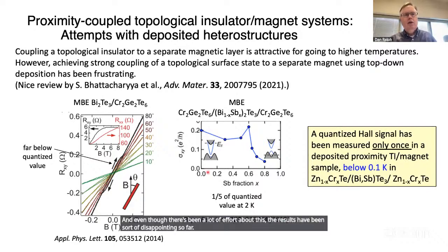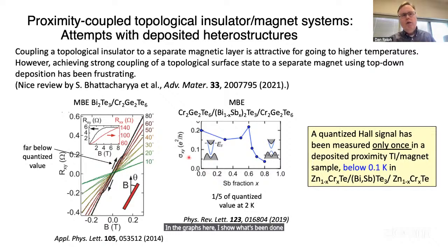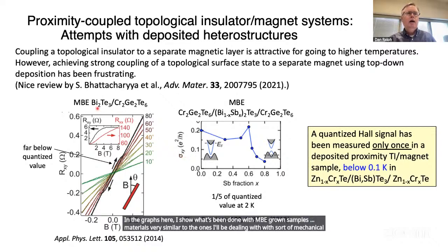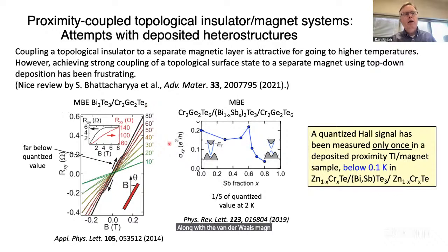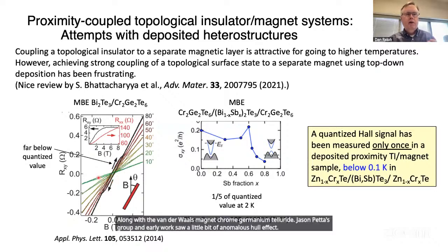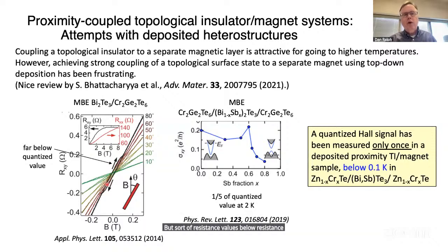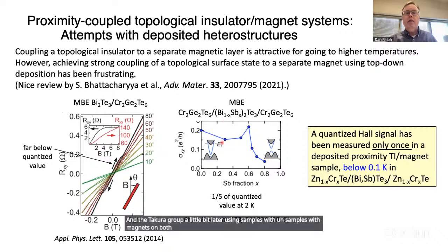In the graphs here, I show what's been done with MBE-grown samples using materials very similar to the ones I'll be dealing with, sort of mechanical stacking, sort of the 3D topological insulator in the bismuth selenide or bismuth telluride family, along with the van der Waals magnet chromium germanium telluride. Jason Petta's group in early work saw a little bit of anomalous Hall effect, but sort of resistance values on the order of 0.1 ohm. And the Takagi group a little bit later, using samples with magnets on both sides of the 3D topological insulator, saw values of the Hall conductivity about 1/5 of the quantized value at 2 Kelvin.